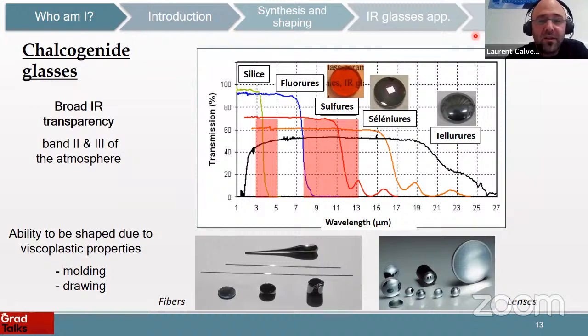So these chalcogenide glasses are transparent in the infrared. If we look at this graph, we can see that silica tubes and silica windows are transparent from the visible up to 3 microns. And what we will use is sulfur, selenium, and tellurium glasses. We can see that they are transparent in the second and third atmospheric windows that we are going to use for all the applications. They are very interesting because, as I told you, they present viscoplastic properties, so they can be very easily shaped by molding into lenses or by drawing into fibers. So here you have some examples of fibers.